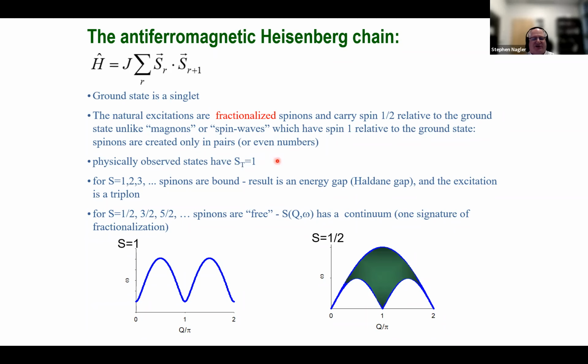And actually, of course, most people will be familiar with this as one of the problems that got a lot of fame for Duncan Haldane, who showed that there's a topological term, if I look at this from the point of view of field theory, so that if I have an integer spin at each site in the original Hamiltonian, these spinons are bound together, and I get a sharp mode with a Haldane gap. If I have, on the other hand, half-odd integer spin, the spinons are free in a sense, and then S of Q and omega has a continuum, as I showed on the previous slide, which is a signature of fractionalization. And in fact, this has been seen, both the Haldane gap and the free spinons,